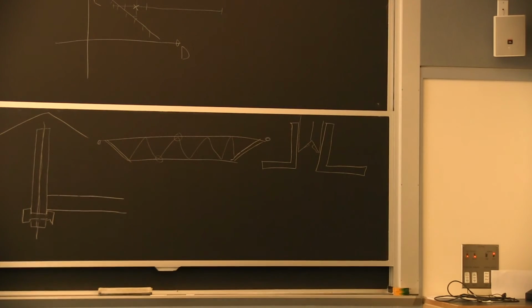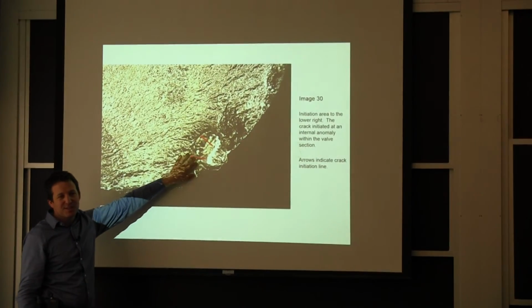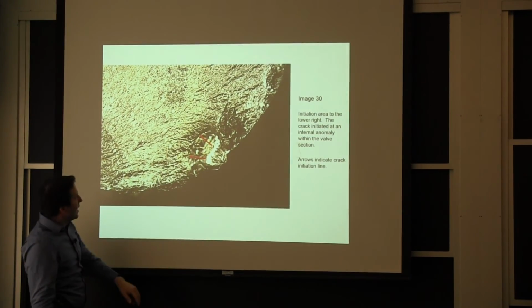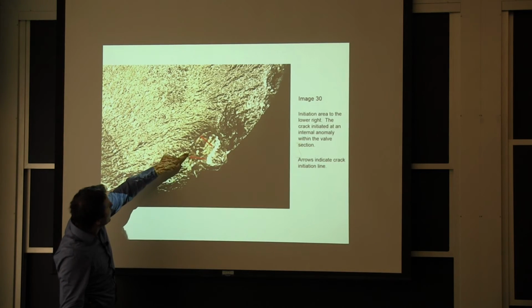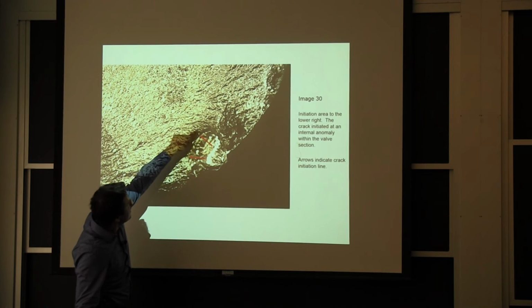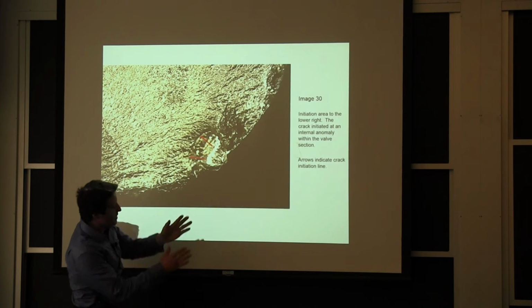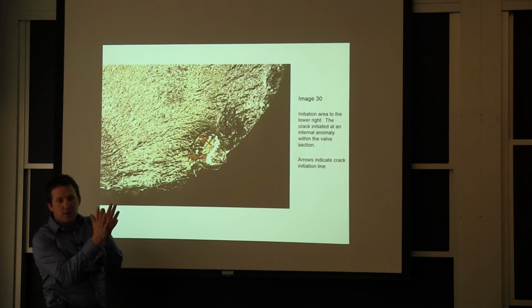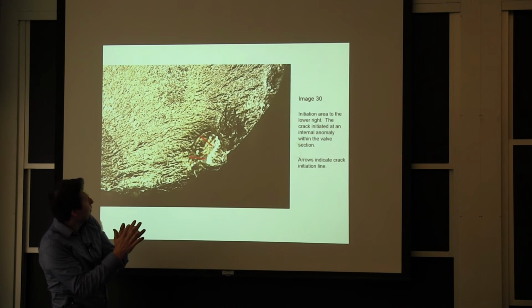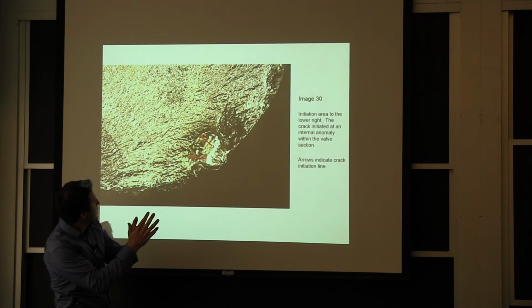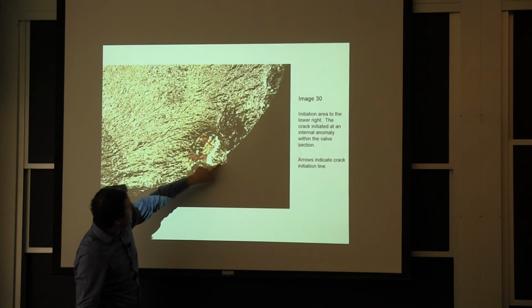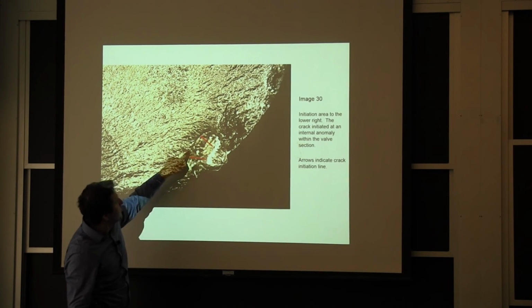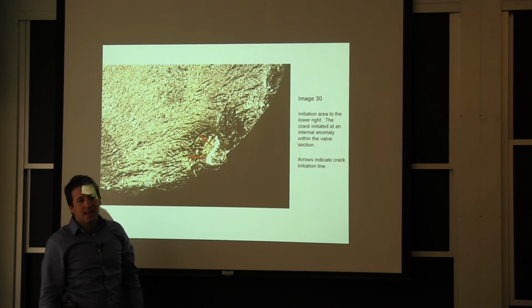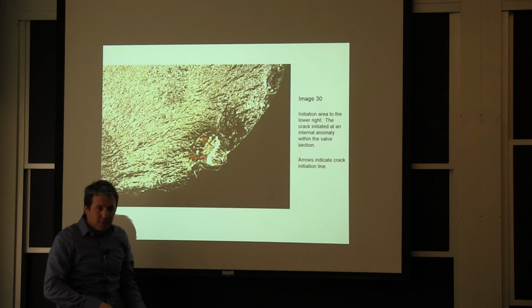This is where I get interested, because what's this? A hole. It's out of focus under the microscope, so there's just nothing here. And what I can say is the crack started here, here, here, here, here. These are all initiation sites, because this is where I have my crack propagation lines starting to diverge from each other. So it means that I had this hole before the crack started. This is not a corrosion pit that happened after starting the crack.